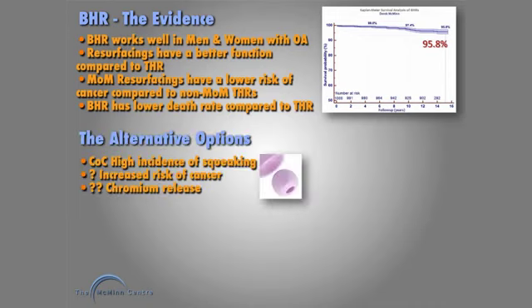I've shown you my concerns about delta-delta ceramic. There's a published 31% incidence of squeaking of these articulations. Certainly delta-delta is in the group of implants on the National Joint Register with an increased risk of cancer, although I must stress that the higher cancer rate has not been attributed specifically to the delta-delta joint. I've shown you chromium release, and there's a worry about what sort of chromium that is. Could it be chromium 6? Because that is certainly not harmless. A lot of work needs to be done on this.